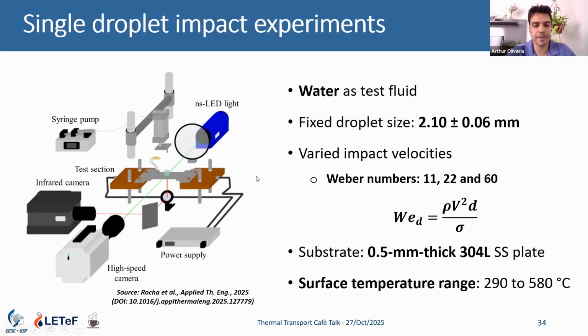For the infrared measurement, we paint the back surface black with a black matte ink. That's actually one limitation we're now studying, because we're starting to measure the thickness of this ink that may or may not influence the estimates. So the back surface is painted black to enhance the signal for the infrared camera.